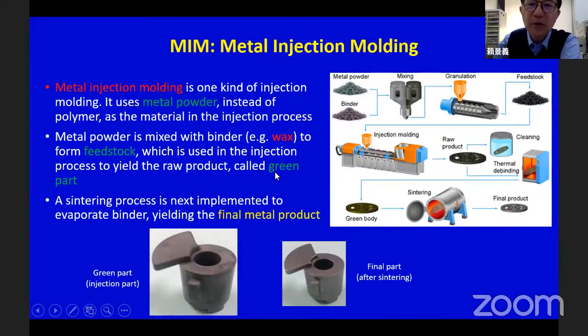This is still not the final product, because the green part still combines the metal powder and the binder. So finally, we need to use a process called sintering to remove the wax, to remove the binder, and to come out with the final product. And the final product is purely metal. So this is our final product. This picture shows the green part. It combines the metal powder and the wax, but it is not so strong. It is easy to be broken. And after the sintering, we get the final product.